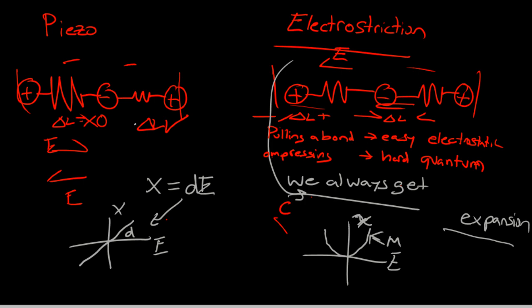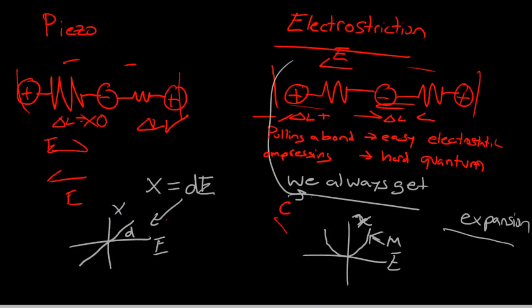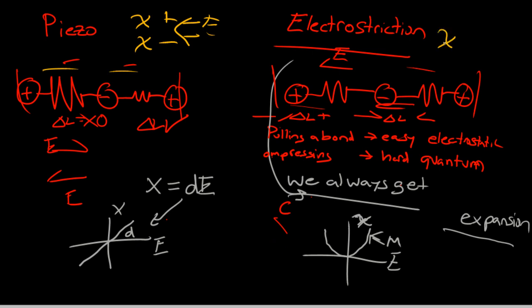So this was the explanation of piezoelectricity and electrostriction. We started with just talking about polarization — why we need polarization, or a non-centrosymmetric structure, which is a polar material. And how, using a spring model, we can understand a strong spring and weak spring model for piezoelectricity. Which allows us to have both a positive strain and a negative strain from an electric field. But in the case of electrostriction, we could only get positive strain. So this is the difference.